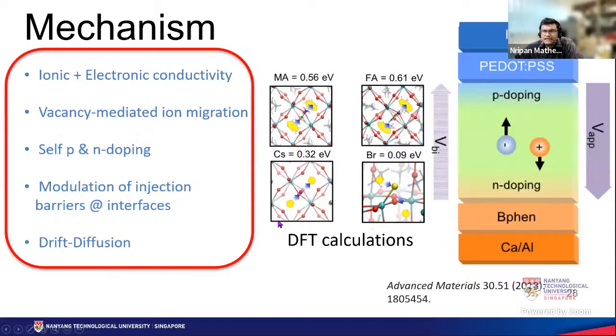So in order to understand what is happening over there, we also did DFT calculations to understand the activation energy for the diffusion of the ions within it. Paradoxically, MA and FA, which have the higher activation energy for diffusion, seem to show us the strongest effect. And that we suspect is because the cesium, which should diffuse more easily, and bromine, which also should diffuse more easily, can also relax back fast. So in the time scale of the measurements that we are doing, MA and FA pop up because they are the ones that have not self-diffused back into their locations. And that is how we are able to see stronger effects for these kinds of perovskites.